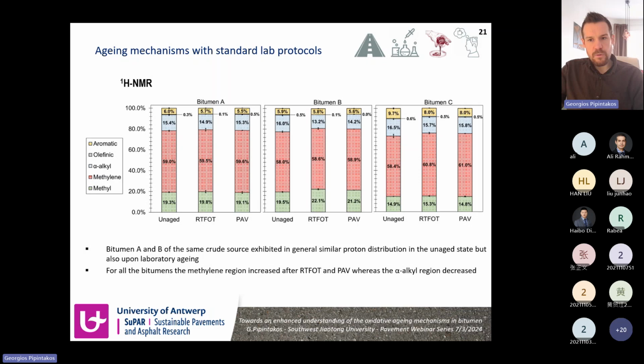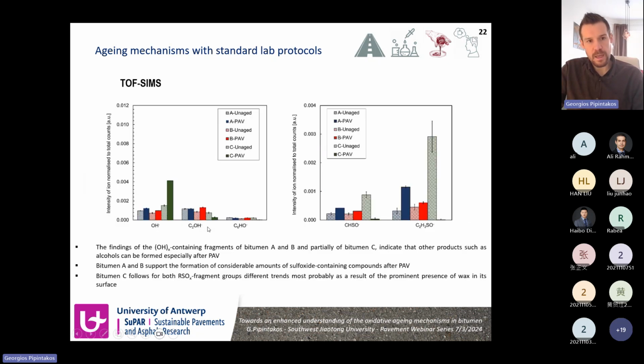And we observed from these results that bitumen A and B, which were coming from the same crude, showed the same chemical fractionation or proton distribution in the unaged state, but also after aging. And for all bitumens, there was an increase of the methylene proton region and a decrease of the alpha alkyl region. So this provides, let's say, stronger information on the differences in chemical fractions of bitumen with aging.